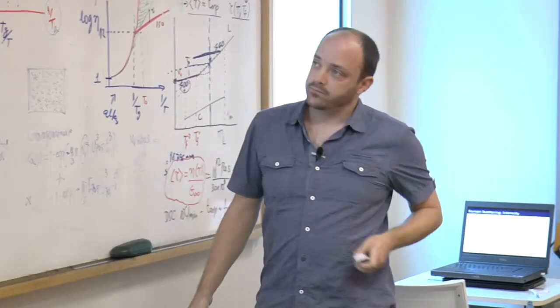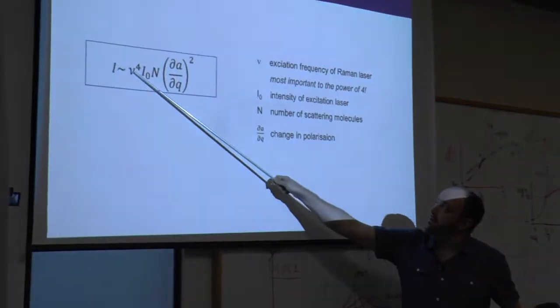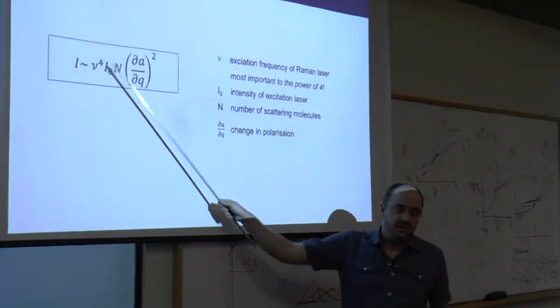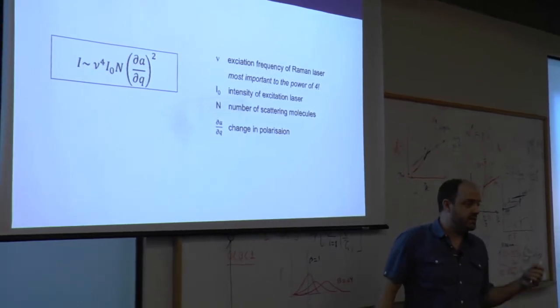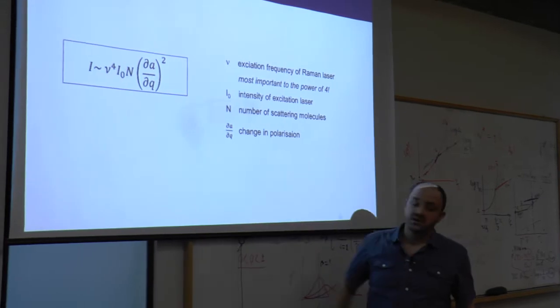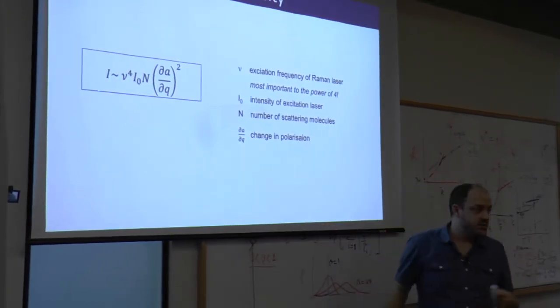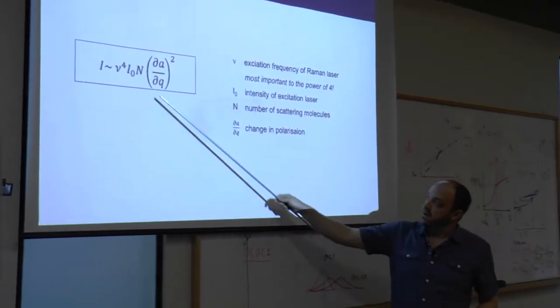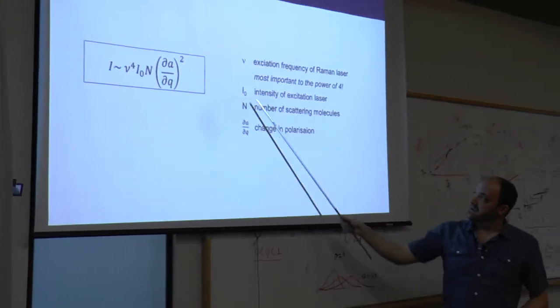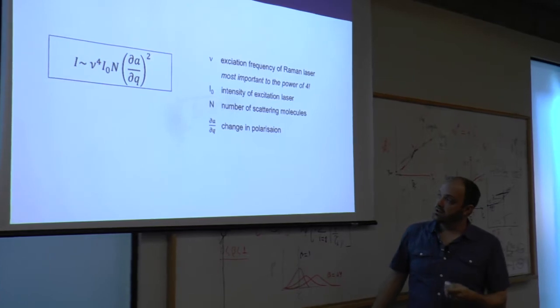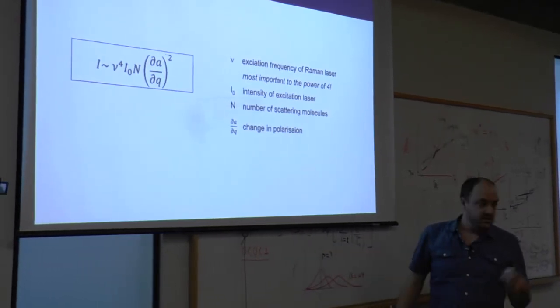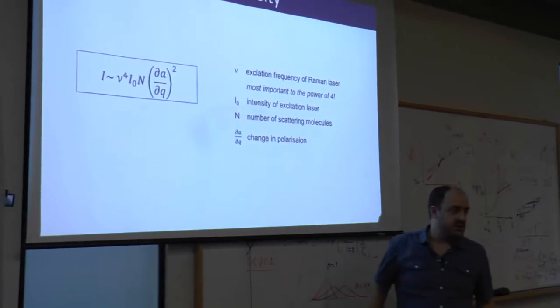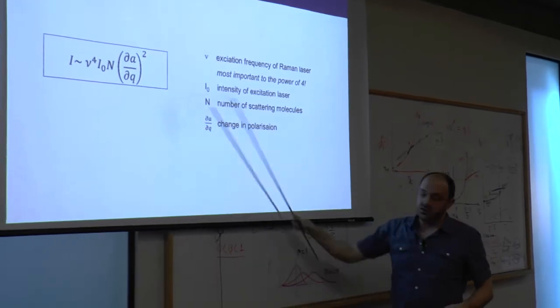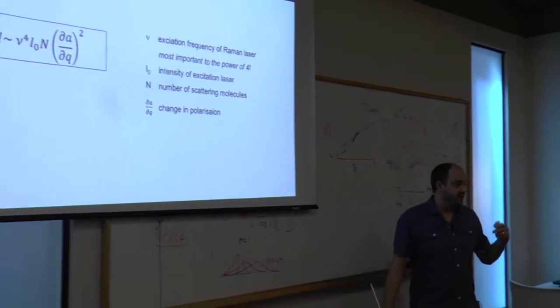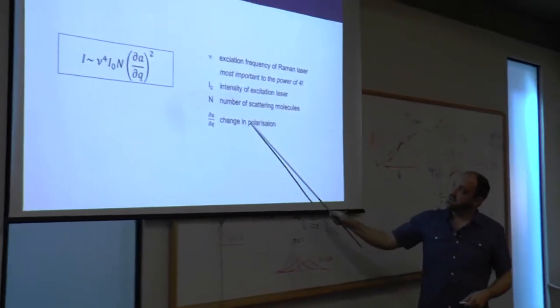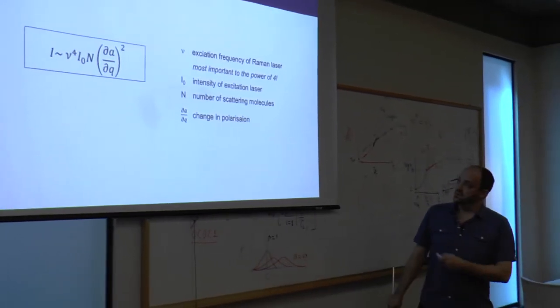So looking at the intensity, it's proportional but not directly proportional to the excitation wavelength. So the laser that you're using for the samples, some lasers are good for some samples. We mentioned ones that are good for biological materials, some that are good for inorganic materials. That excitation wavelength goes to the power of 4 in terms of the intensity. So it's really important in choosing the right laser for the job you're looking at. Also, how intense the excitation is, so how much light you're actually getting on the sample, how much power is in your laser, how many molecules you're actually sampling, and this change in polarization, which goes to the square. And we're going to see how this polarization changes for some of the materials, specifically for silica, and then anything you add to the silica. So the most important factors, this polarization and the frequency of the laser you're using.